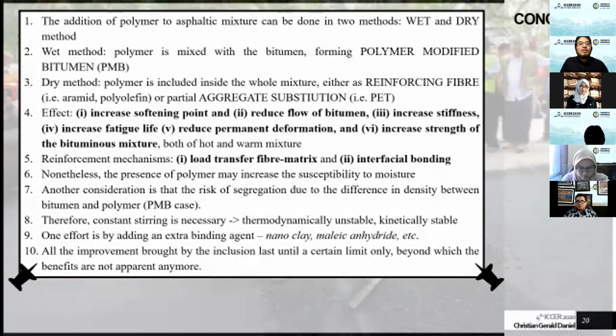There is a risk of segregation in PMB due to the difference in density and the weak bonding between bitumen and polymer, therefore constant stirring is necessary. It's thermodynamically unstable but kinetically stable. We could also have binding agents or additives. And the most highlighted point is that the benefit lasts only until a certain limit, as we have seen, beyond which